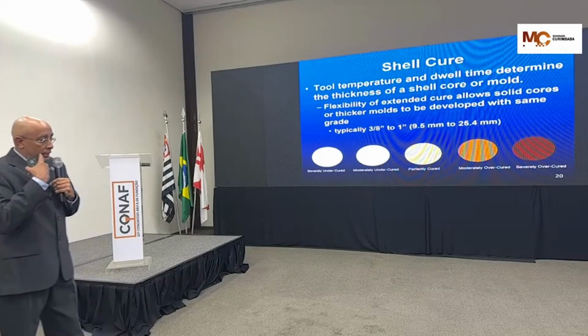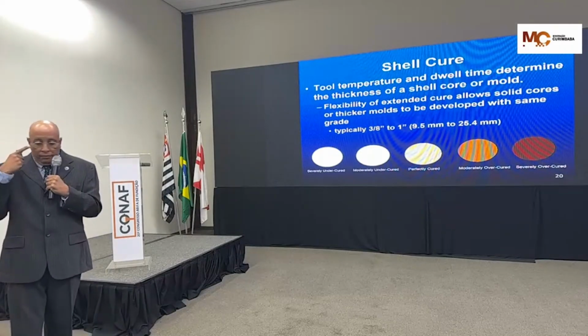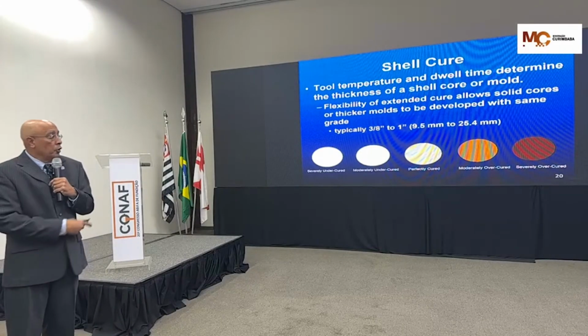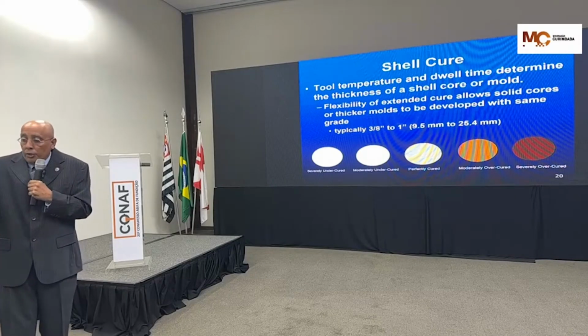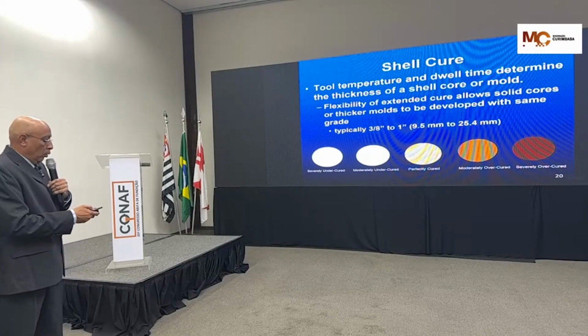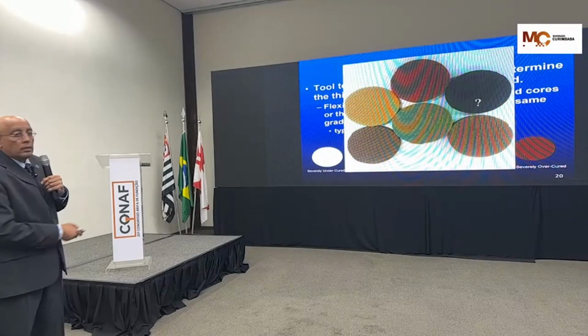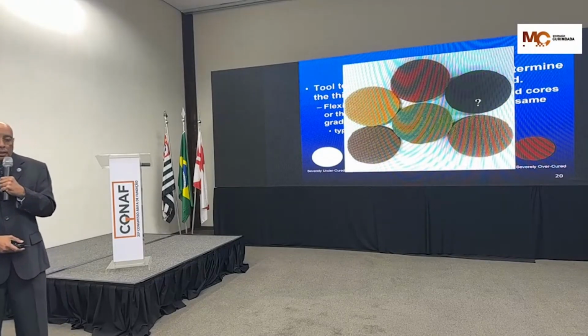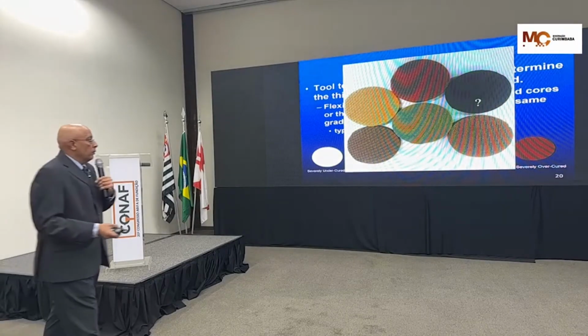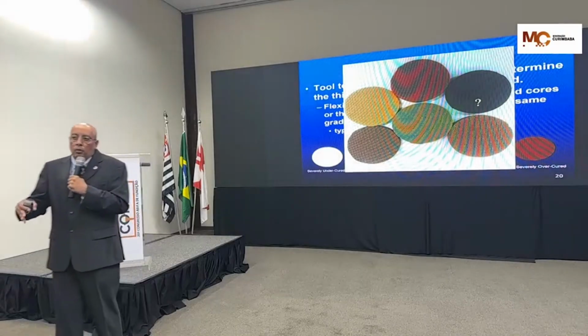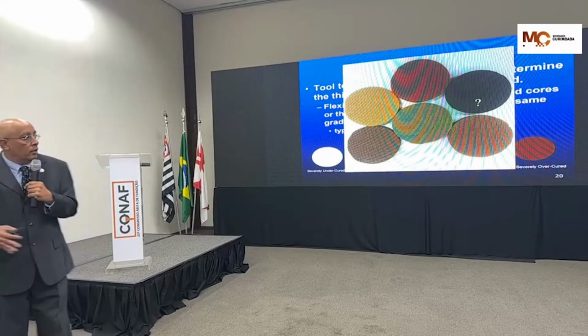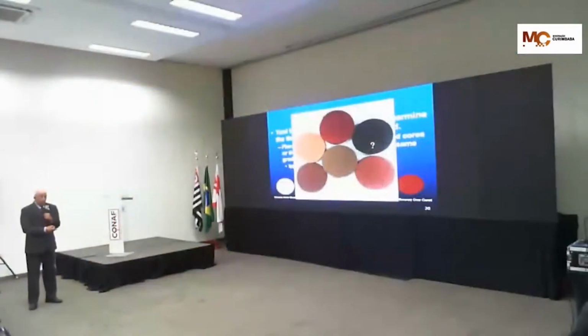Now, that's what I might be seeing with my eyes. If you have better than 20/20 vision, you might be seeing a different color. We know we don't always see that the same. But now, what if that sand is an opaque sand? We do not know when we are cured. So this is why we need qualification techniques around this chemically bonded sand process, and we'll show you how we establish the optimal conditions for this process in cure.